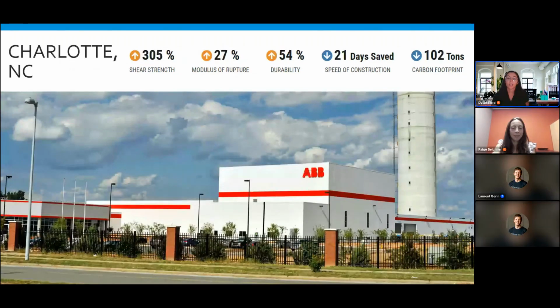And then a type of project that we do, I would say it's probably our bread and butter, is large scale distribution and warehousing. So heavy industrial slabs. This is one that we did in North Carolina. This slab originally had 2 layers of number 5 bar, so 1 top, 1 bottom, at 12 inches on center each way. And we were able to go in and fully remove all of that bar so that all they had to do was mix fiber in and go. It's approximately like for every 10,000 square feet of slab that you're doing, you'll save a day by switching to a fiber option. So if it's a tight schedule, it really can be beneficial.